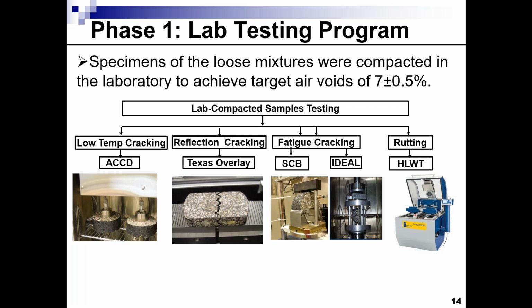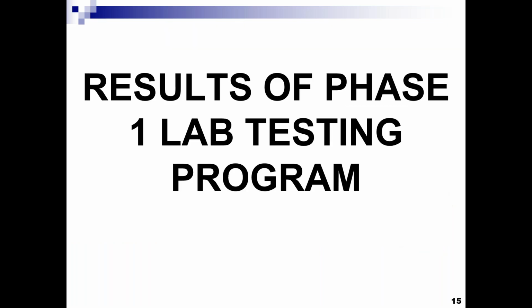All mixes were compacted at 7 plus or minus 0.5. So in all tests we were targeting an air void of 7 plus or minus 0.5, because most of those test procedures recommend using mixes that are compacted at this compaction level. So I will be talking mainly about the results, and again, due to the limits, we will be just focusing on some of the results, not all the results.